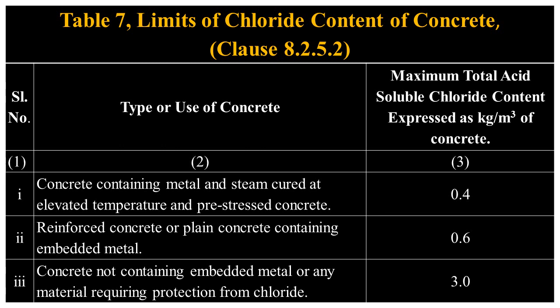Serial number 1, type or use of concrete: concrete containing metal and steam cured at elevated temperature, and pre-stressed concrete. Maximum total acid-soluble chloride content, 0.4 kg per cubic meter of concrete. Serial number 2, type or use of concrete: reinforced concrete, or plain concrete containing embedded metal. Maximum total acid-soluble chloride content, 0.6 kg per cubic meter of concrete. Serial number 3, type or use of concrete: concrete not containing embedded metal or any material requiring protection from chloride. Maximum total acid-soluble chloride content, 3 kg per cubic meter of concrete.